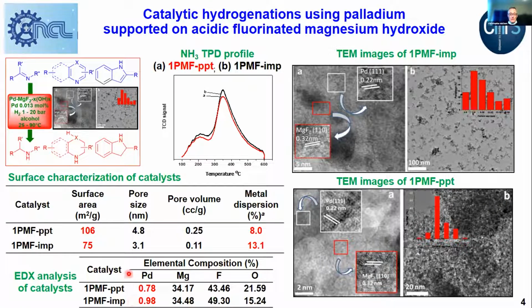In addition, the elemental composition obtained through EDX analysis of the catalyst showed a higher content of palladium for the impregnated catalyst by comparison to the precipitated catalyst. TEM images of the catalyst allow us to characterize the palladium nanoparticles and the magnesium fluoride nanoparticles according to their d-spacing values. We could notice that the average particle size for the precipitated catalyst was about 7-8 nanometers. And regarding the impregnated catalyst, we had a broader distribution of particles with 5-16 nanometers particle distribution.